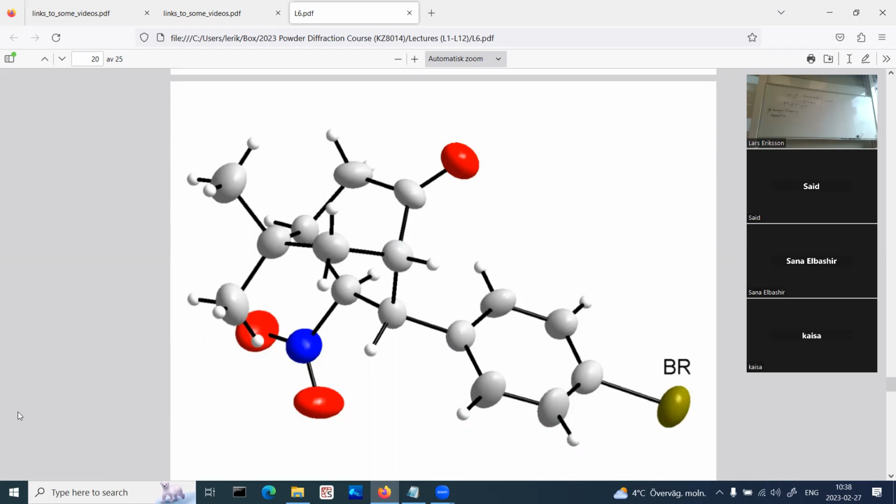Finding the bromine atom gives structure factors quite okay, enabling us to reconstruct the rest of the atomic positions. And bromine is a heavy atom for X-ray: atomic number 35, so 35 electrons, while carbon atom is much lighter. But for neutrons, not necessarily.